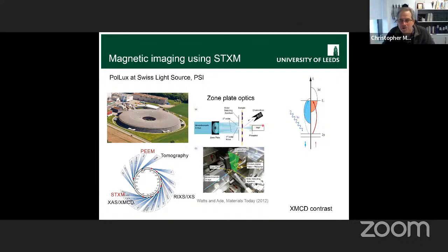And the way we get magnetic contrast is using this effect called X-ray magnetic circular dichroism. In that effect, your X-ray photon comes in, and it can promote an electron from these 2p levels up to the Fermi level. And because of the quantum selection rules, the circular polarization of this light depends on whether you pick out spin up or spin down electrons. And then because at the Fermi level there are more states available for one spin than for the other, it's easier to promote one or other spin. In this case, it would be spin up.